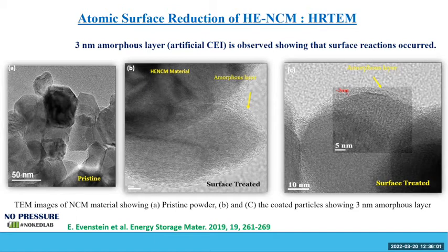The only way to really answer this question is to invest a lot of time in TEM for billions of particles. This is a small portion. The way this particle looks, you have a sphere of maybe 3 to 5 microns, and this sphere is really composed of small crystallites. When we look at the crystallites, we couldn't find a crystal that is not coated. I cannot say based on that that all of them are coated. I can just say that we looked at many and they are not uncoated, but there are gazillions. Okay, so they are coated.